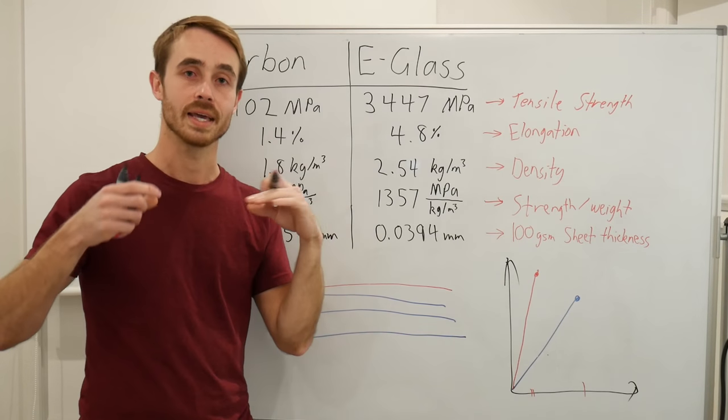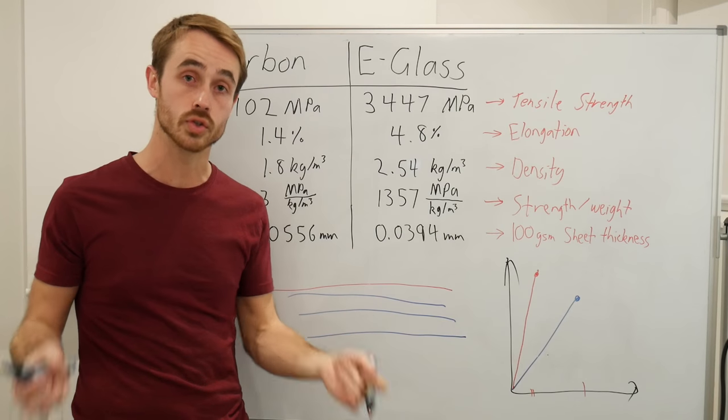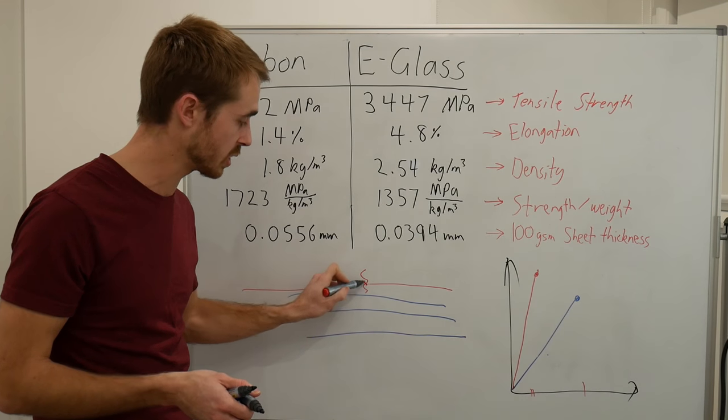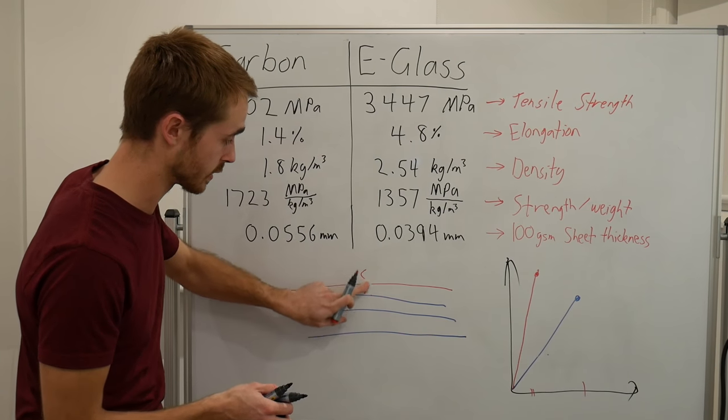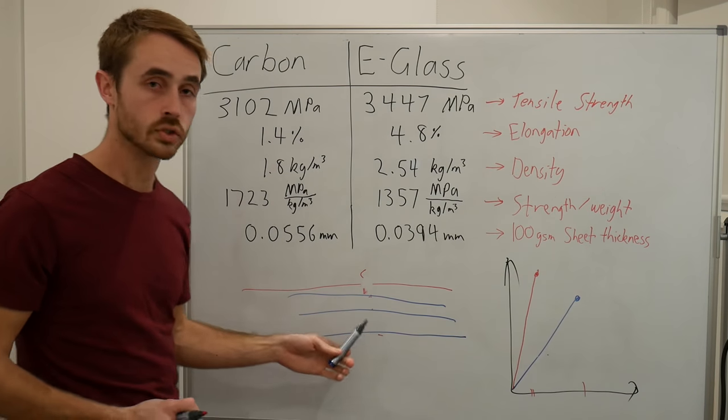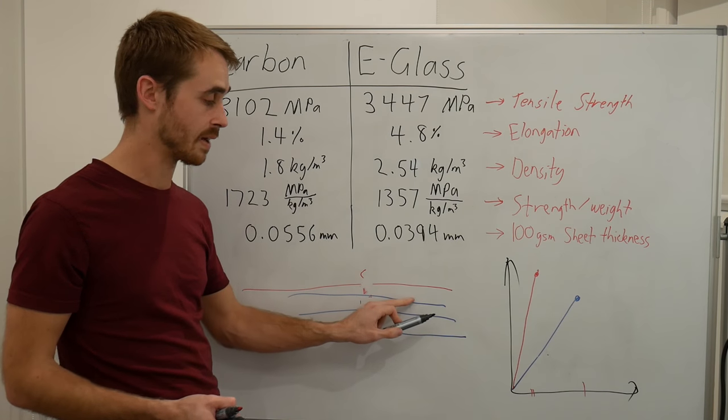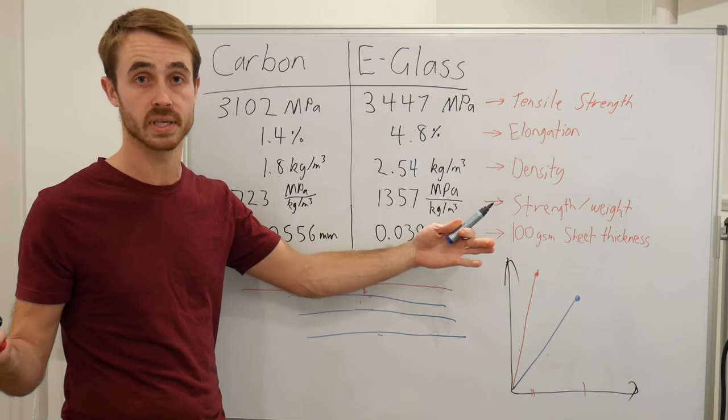You've broken your carbon, it's all transferred to the fiberglass, which means the carbon fiber isn't actually doing anything at this point. We've basically just created a split in this carbon here, and because this has essentially been removed, all the load is here. So effectively what we've achieved is we now just have a three fiberglass layer structure. It's like the carbon was never even there in the first place.